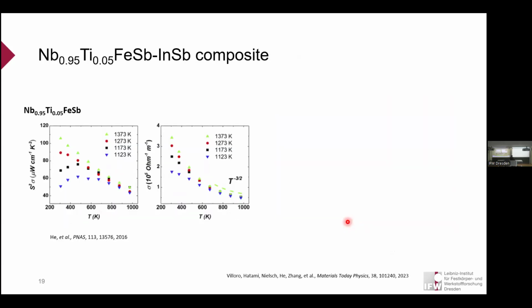So with this knowledge, we take my own material, which I developed like 8 years ago, niobium, iron, antimony, another half-Heusler, and we dope with titanium. What we found is that if we increase the sintering temperature for this material, we can have a significant performance gain by a factor of 2 because we have a higher conductivity. And then we want to see whether we can realize a similar conductivity enhancement without necessarily increasing the grain size by increasing the sintering temperature or whatever.